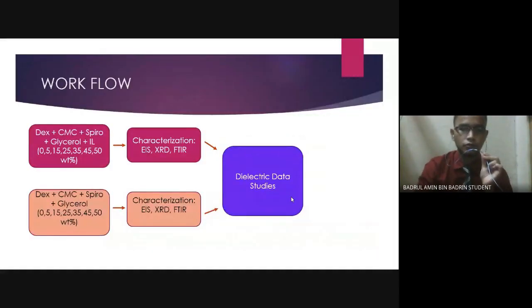So this is the workflow of my studies. In my research, I make a hybrid of 5 materials, which are dextrin from potato starch, which we call DEX, as stated in the diagram, CMC, carboxymethyl cellulose, a carbohydrate derived polymer, and then we have Spiro as a salt donor, a charge carrier donor in this study, glycerol and ionic liquid. So the hybrid of 5 elements or materials is stated as the second system.